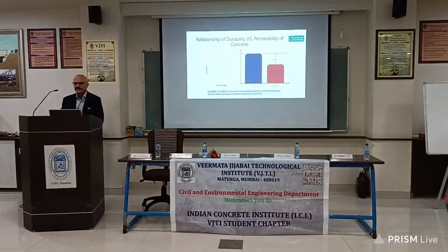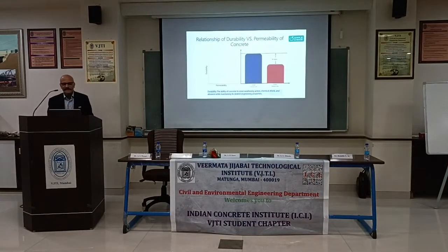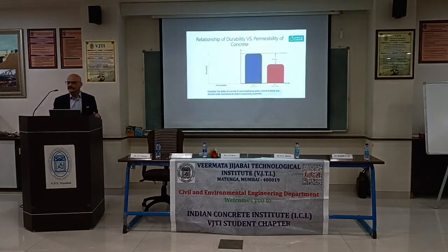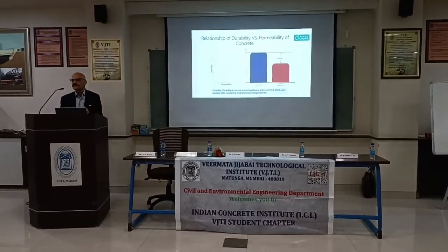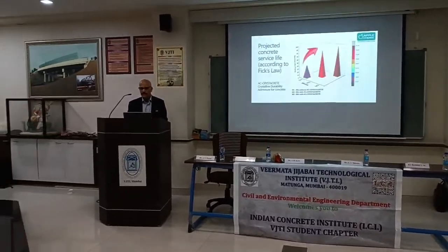See, there is a direct relation between durability and permeability. If the permeability is more, durability will reduce. And when the durability reduces, then the useful life of the structure also reduces. If you go by Fick's law, if you are adding these crystalline durability additives, then there is an additional life of around 60 years to the structure for the same grade. So if you are making 40 grade concrete, you add crystalline durability, whatever is your life of the building, you will be getting 60 years more.